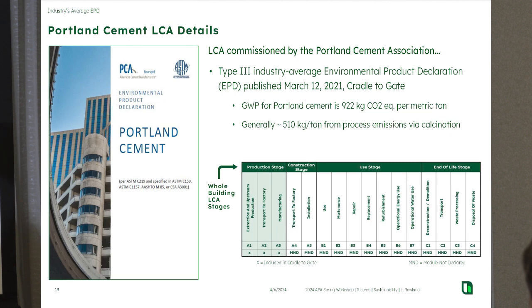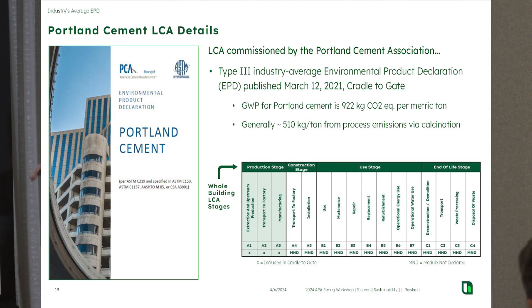So where the rubber meets the road on this is when you start accounting for this, you start counting it up. According to the EPD for architectural precast, they've got this much cement in a typical ton of precast. And precast is a little bit unique. Instead of doing a square meter or a square foot or a cubic yard, they decided that they wanted to use a unit of a ton of precast material, which of course includes the rebar, which includes everything else that's in that precast concrete. In that, their mix calls for 143 kg.